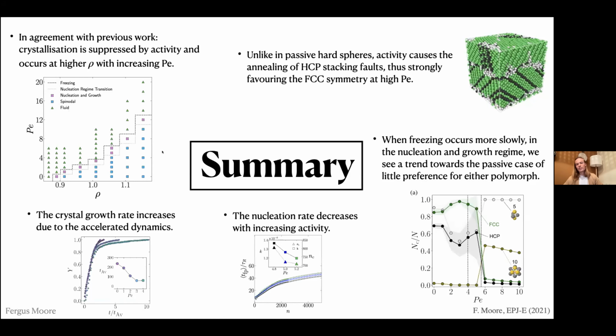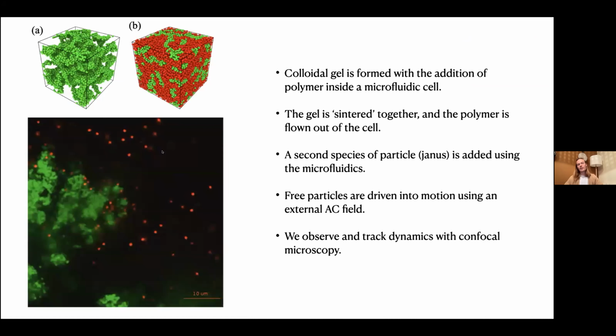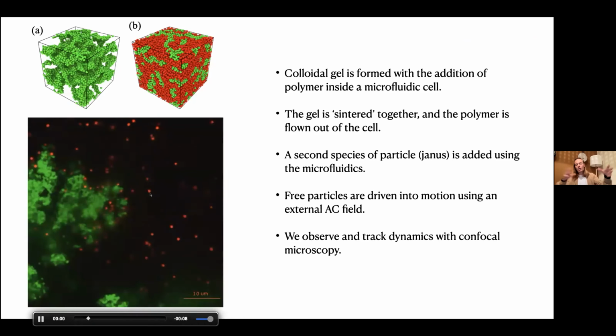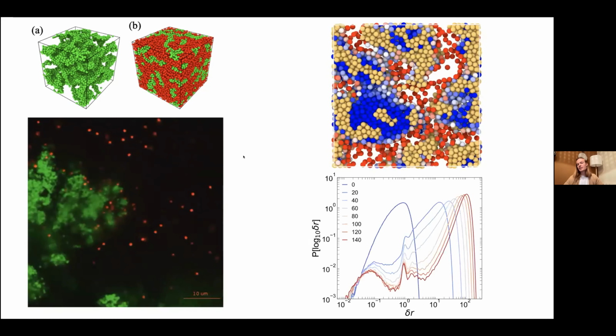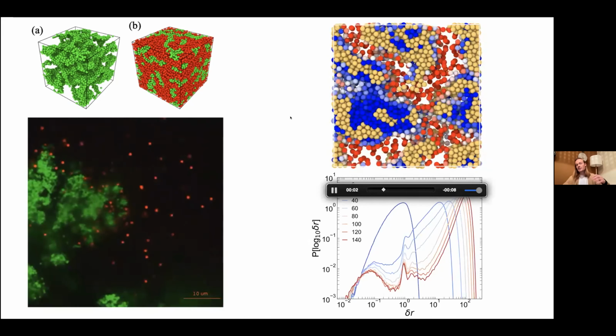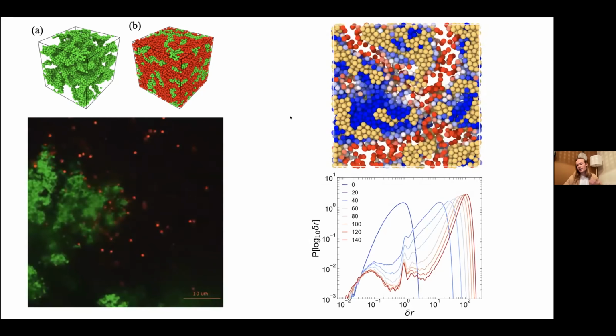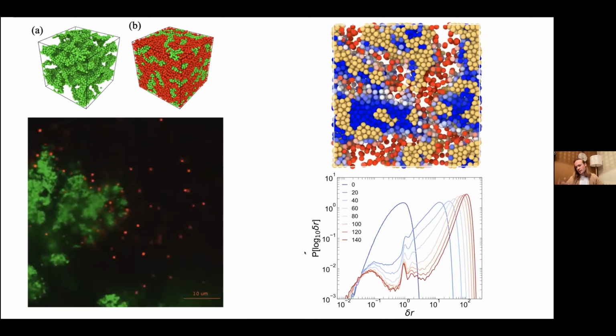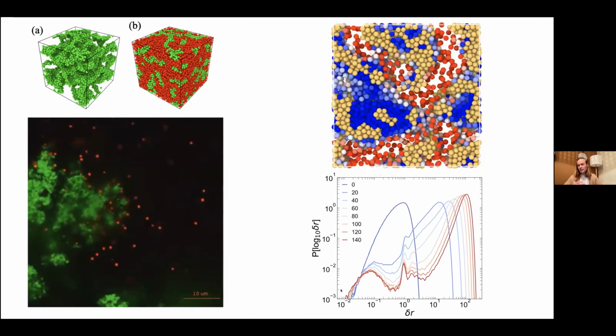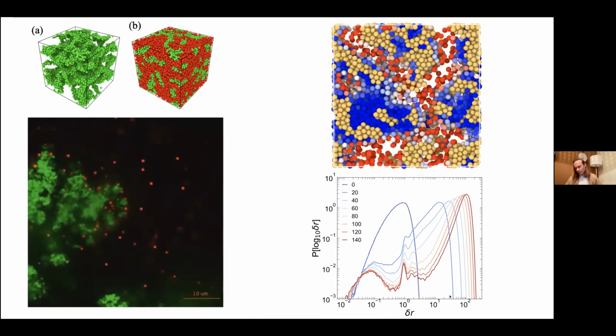And if you'd allow me just one more thing to say, there was an interesting discussion before with Emanuela, where we were talking about particles inside anomalous dynamics. I also get my hands dirty in the lab sometimes, and I make colloidal gels, which are 3D systems, and then I add Janus particles into these that would be made active by electric fields, and this allows us to explore complicated environments, and we're doing some simulations of this. We have a slice, these yellow particles are a gel, and as they move, you find their persistent motion. Some particles collect and get very stuck and have slow dynamics, whereas others are moving very fast. This is a histogram of the displacements, and you see there's a population which is moving very slowly as the Peclet number increases, and there's a population that moves very fast.